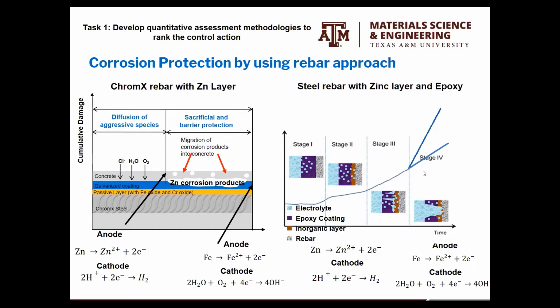All right, and the last system that we are going to cover is when we add the epoxy. The epoxy is another layer that we are adding, and you see there are different stages before the epoxy or the layering of the epoxy, and the galvanized layer will last until we reach the metal. Of course, the normal saying is that the more layers, the better. Well, sometimes no. In terms of corrosion, that's why we are putting the stages. The accumulative damage will take time for the epoxy, but I think there are studies that show and demonstrate that when the epoxy is no longer there, we will have a local condition, and the epoxy is a very nice cathodic side, and this is a very nice anodic side. So maybe the accumulative damage will be higher, all right?